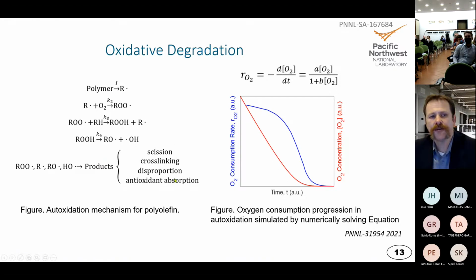So one measure of aging that has been proposed that might track closely with aging, even at mild aging, is the consumption of oxygen in this reaction. If you're having this oxidative degradation, it doesn't happen without consumption of oxygen. So the rate of oxygen consumed, if we're able to measure that, should tell us about what's happening.